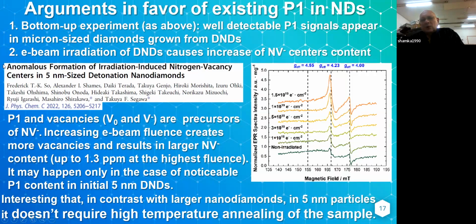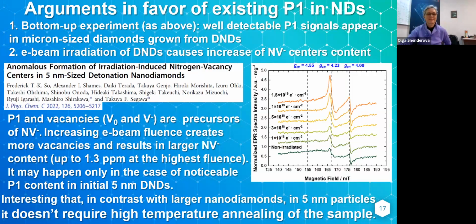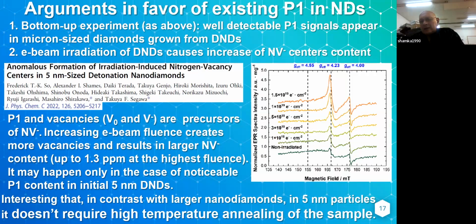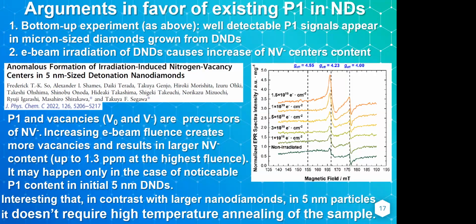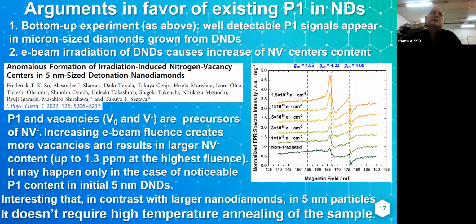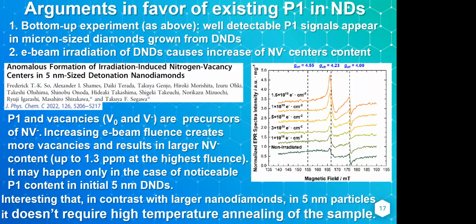Okay, it would be interesting to do it with the smaller sizes. I don't know what is the mechanism of quenching of these dangling bonds, but if it is possible, it would be great. So how about using just a classical Fenton system to generate OH radicals and see what would happen if you treat nanodiamonds with this OH radical? Will this central line disappear or at least diminish? Because it's a pretty small particle, OH radical, if it goes inside the interface layer, why not? If you coat it with silica, it does not mean that silica goes inside the nanodiamond crystal structure. So obviously there is some chemical bonding to those dangling bonds.